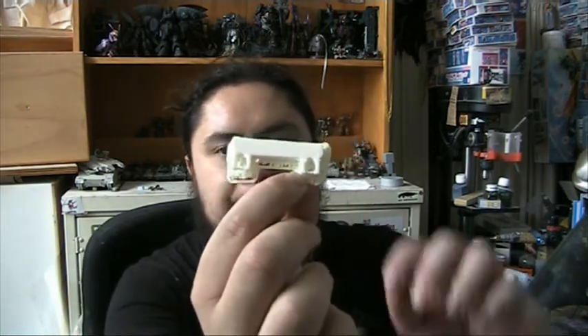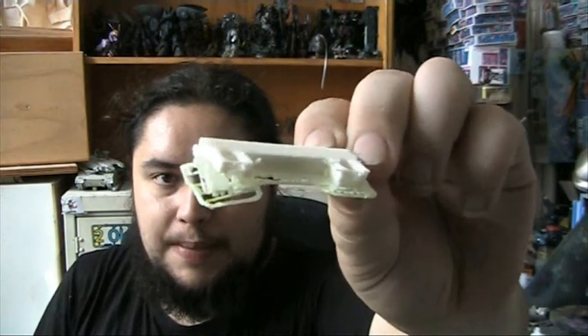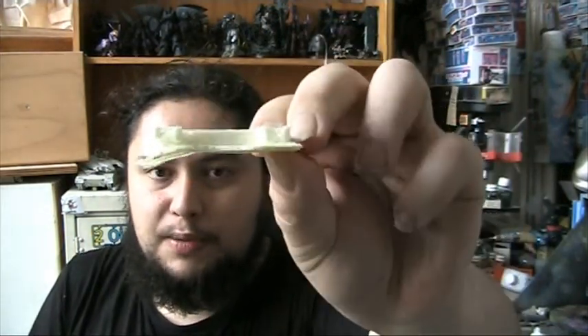Now, I've done a couple of models. I've got this 3D printed component part, and there is all sorts of damage. As I've tried removing the raft, the actual model started disintegrating and ripping to pieces, exposing the center. The walls were quite weak. The support is very strong. The support stuck to the material far too strongly and started tearing it up.